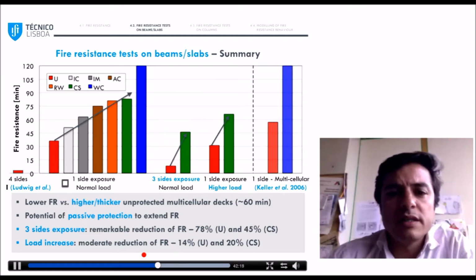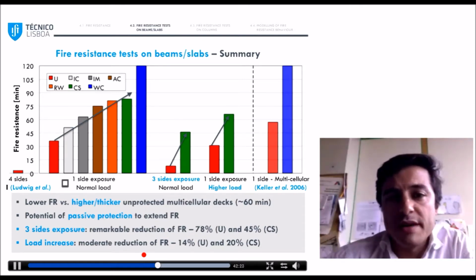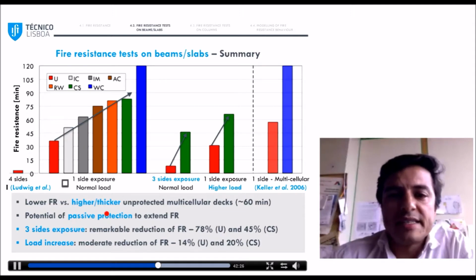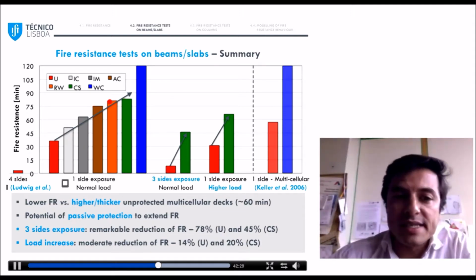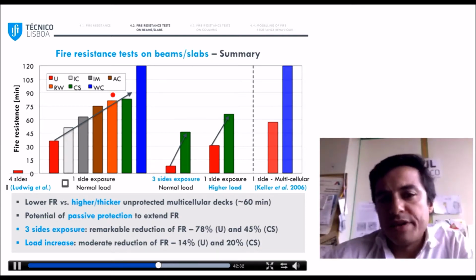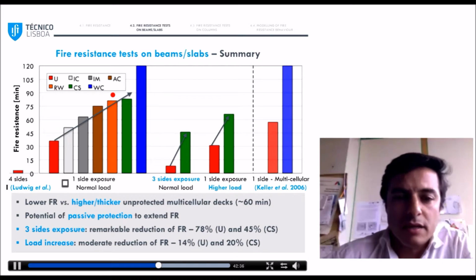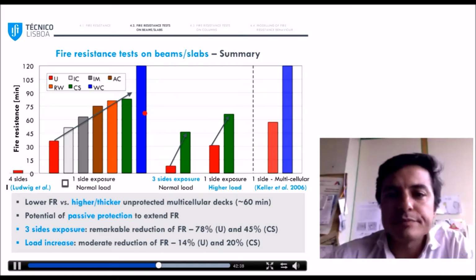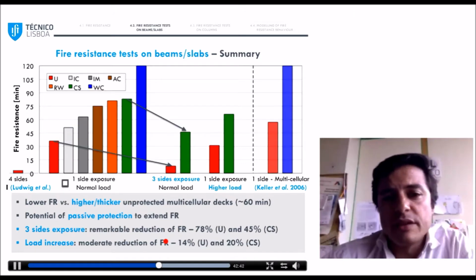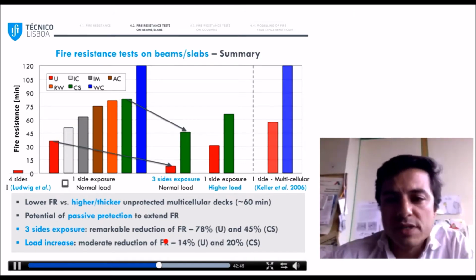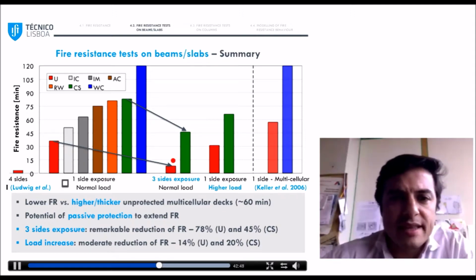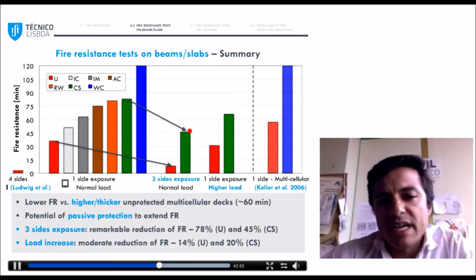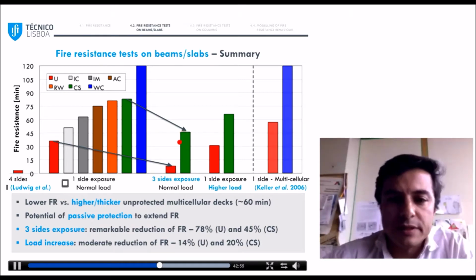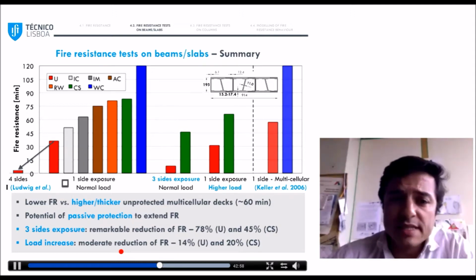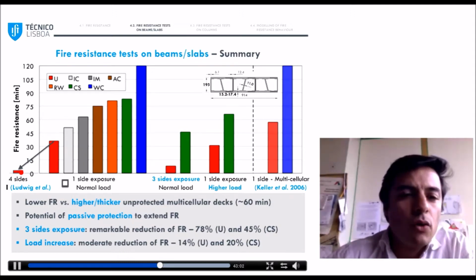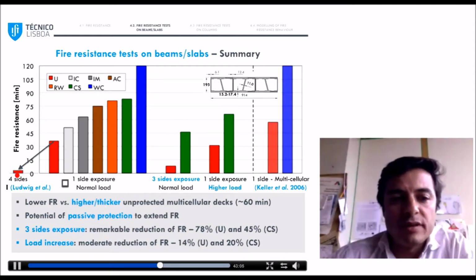Next point I would like to remark is that all passive protections were effective, granting fire resistances higher than 60 minutes for one side exposure, and therefore offering in this case a much simpler and more economic alternative to water cooling. But it's relevant to see how the performance was drastically affected with the three-side exposure. So in this case, even with passive protection, we did not get to the 60 minutes of fire resistance. And these results are consistent with the very low fire resistance that had been reported by Ludwig.